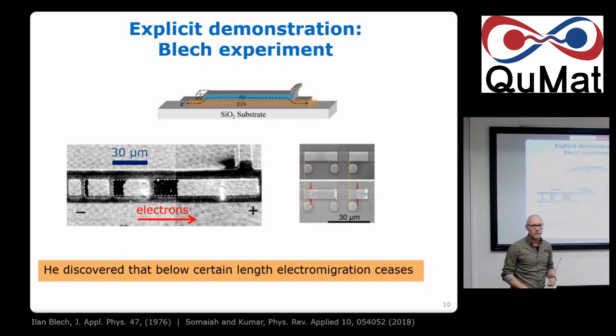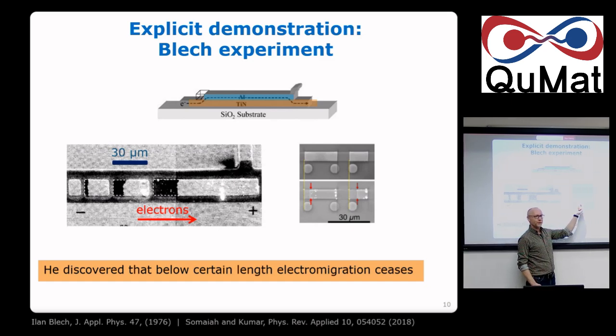Exactly. I'm curious about the electron wind, because the electron wind also depends on, I guess, how much it interacts with phonons and so on. So is there a double amplified effect here if you have a bad conductor? Temperature plays a very important role because this is a thermal activation process, and it's something you cannot get rid of. It comes together. And I'll show you later, it's even more complicated. What this shows basically is that once you get too short, it does not work anymore.